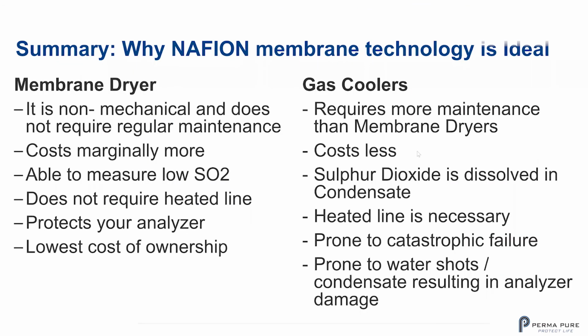So let's do a summary of why Nafion membrane technology is ideal. Number one, Nafion dryers: it is not mechanical and does not require regular maintenance, costs marginally more, able to measure low SO2, does not require a heated line, it protects your analyzer, and has by far the lowest cost of ownership. Gas coolers are the most common technology. They require more maintenance than membrane dryers. They cost less. SO2 is dissolved in the condensate. A heated line is necessary. They're prone to catastrophic failure and prone to water shots or condensate, resulting in analyzer damage.